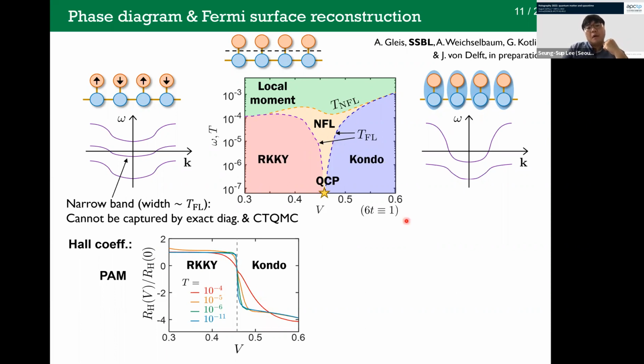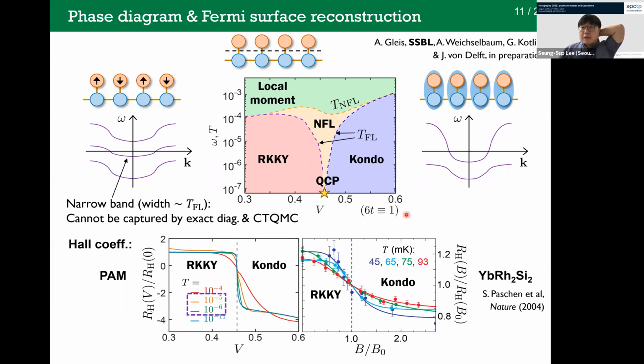liquid regime. Actually, this kind of jump was also found in the real material, ytterbium rhodium disilicide, YbRh2Si2. So the experimentalists have found this jump, which gets smeared out as going to the higher temperatures. So this range of the real temperature corresponds to our temperature parameters in this range. And let me note that here in this material, the phase transition is driven by applying the B field, which we didn't. Here we used V as a driving parameter. But it is quite interesting that our simplified model could capture the key ingredients of this experimental data.